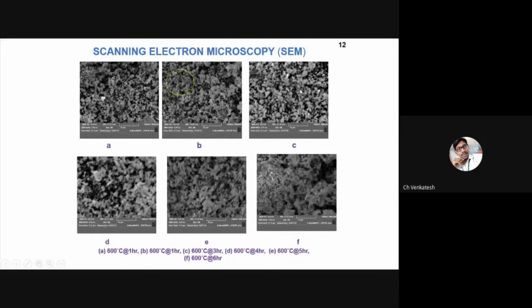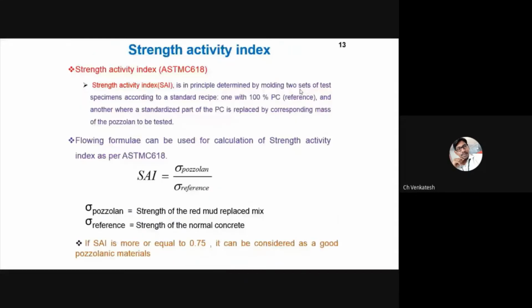So in the physical properties, we have identified that up to 2 hours of heating, the particles are losing their moisture. That's why the physical properties are reducing. After 2 hours of heating, an increasing trend was observed due to agglomeration between the particles. From this SEM analysis also, we can justify that after 2 hours of heating the agglomeration takes place. So I am saying there is a good correlation with all the physical properties.